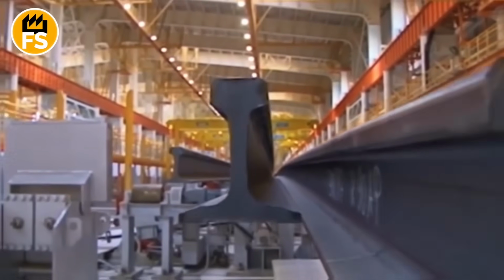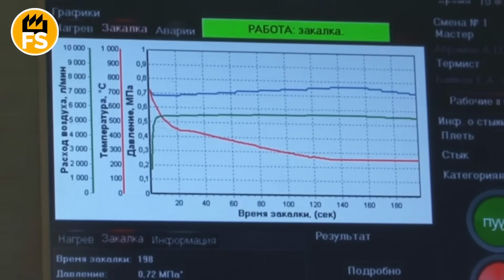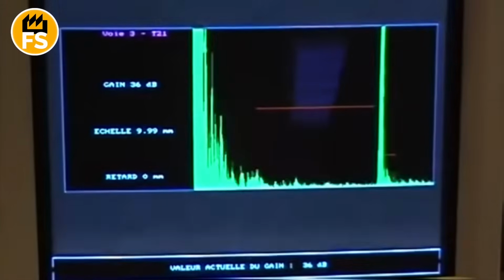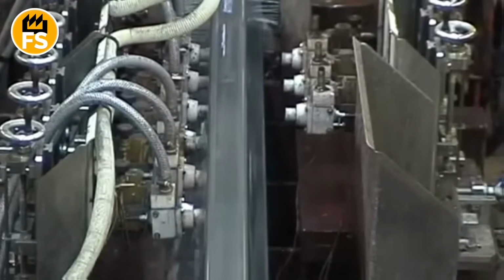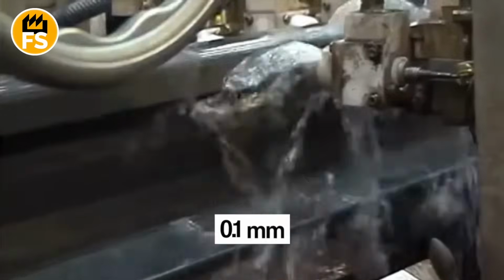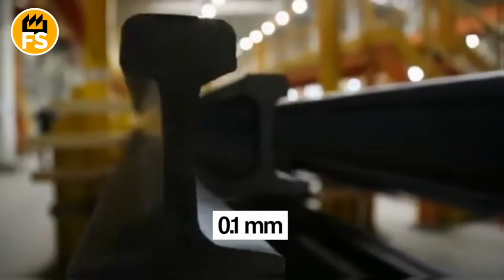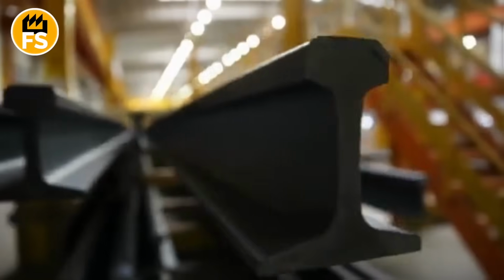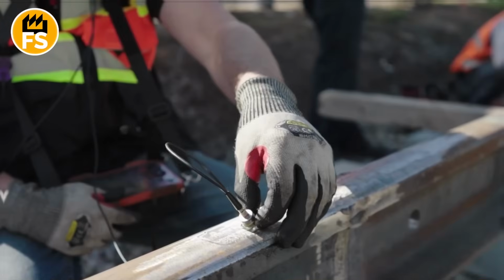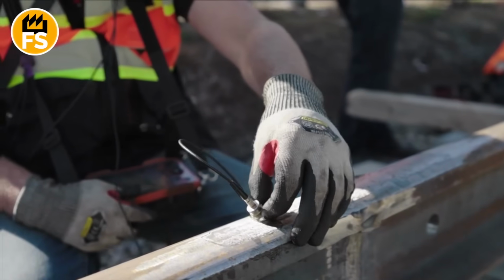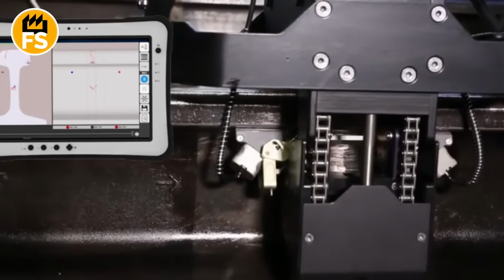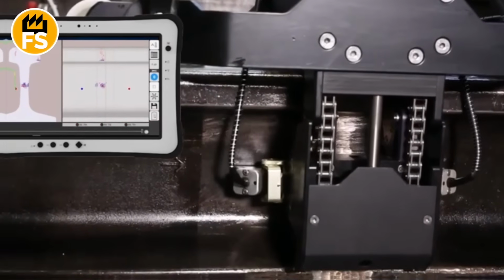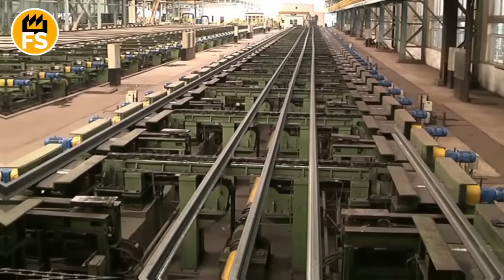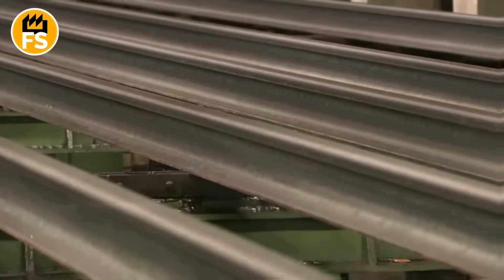That tragedy completely transformed how subway rails are made and tested. Today, after cutting and drilling, every single rail goes through what's basically the most thorough inspection process you can imagine in Building 6. Ultrasonic testing machines send sound waves through the entire length of steel to detect any internal cracks as small as 0.1 millimeters deep. Defects that are completely invisible to the human eye, but could be catastrophic. The rails also get checked by laser systems that measure straightness within 3 millimeters across the entire 39 feet. And surface scanners look for any pits, scratches, or rough spots on the head, where the train wheels will be riding.